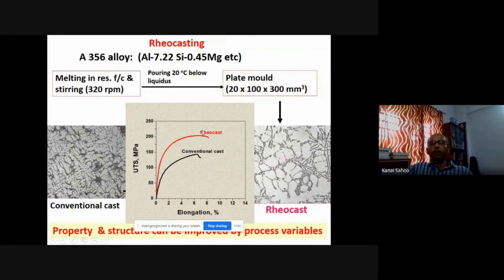For example, if you do the conventional casting of the same alloy, aluminum silicon alloy, you get around 120, but rheocasting will give you around 200 with a slight improvement in ductility. But you can notice that the primary aluminum is globular, but all this dendritic structure is still elongated, around several microns, more than 50 micron. Please note this, more than 50 micron. So we'll see in our process how this 50 micron can be converted into a few nanometers. Okay, and all these alpha grains can again be reduced to a smaller size to improve the strength multiple fold.